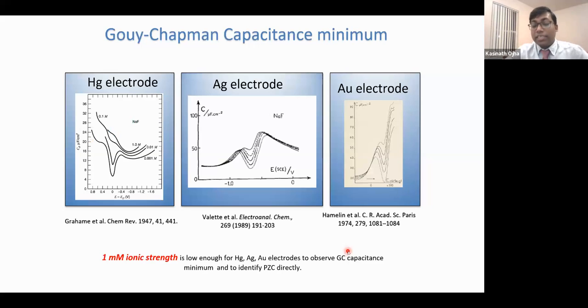And it's not just a theory, experimentally, people have found those capacitance minima. So this is a very standard classical measurement, 1947 by Graham, on a mercury electrode. They got, at different electrolyte concentrations, a capacitance minimum right at the PZC. Same for silver electrode and gold electrode, they found the capacitance minima at different electrolyte concentrations. Basically, if you go to very low electrolyte concentration, then only you will be able to see these minima.